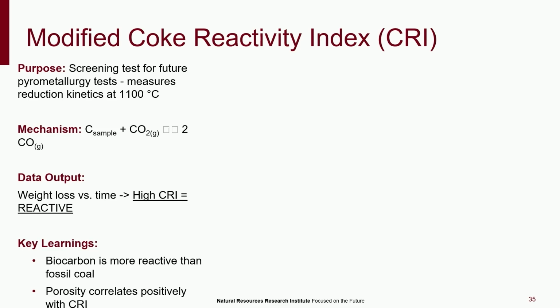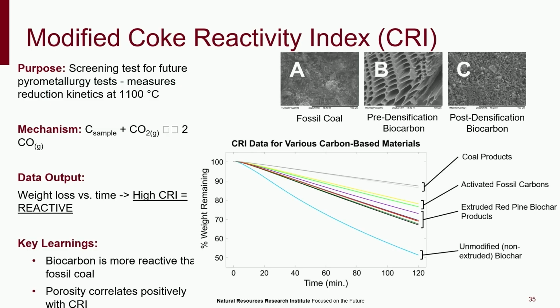One of our metallurgical tests that we did was a modified coke reactivity index. So we basically take the carbon sample and then measure the weight loss over time in a high temperature environment. And then a high CRI means it's very reactive. So here you can see, I have a graph here. Where are we? Here we go. So the weight remaining is on the y-axis, and then time in minutes is on the x-axis.